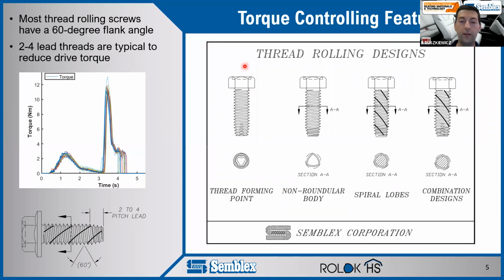Now, torque controlling features are very important for thread rolling fasteners. If we look at this graph on the left, this is a drive to failure curve, so this is what we run whenever we want to figure out what tightening torques we can use on an assembly line. We look at this curve, we see two different peaks. The first peak here is what we call the drive torque. This is the torque it takes to form threads into your material. Once you've reached this top torque value, you form threads all the way through your part. After that, you're simply just running the screw down until the head touches, which is right here. Once that head touches, your fastener starts to stretch, you start to generate clamp, and then if you go too far, something breaks. That could be the female part strips, the fastener breaks, or the fastener thread strip off.